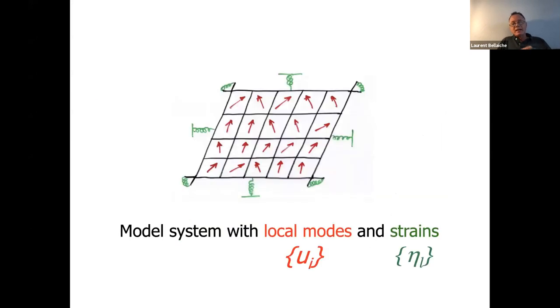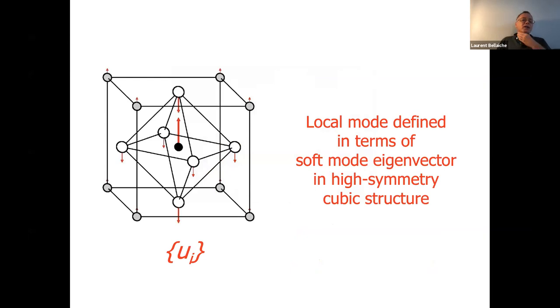And in fact, this is a nice representation. In each five atom unit cell, you have local modes and you have strain. So if, for instance, the local modes are parallel to each other in all the unit cells, you are talking about ferroelectricity. If they are anti-parallel to each other, you are talking about antiferroelectricity. And how it is defined, Professor Diéguez really explained that very well yesterday. It's basically the local mode is defined in terms of soft mode eigenvectors. You can use the dynamical matrix, but most of the time we use the force constant matrix to define these local modes. And you get it from the high symmetry cubic structure.